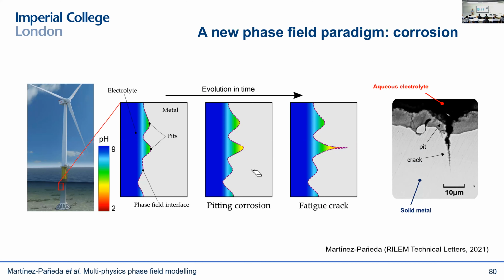It is a complicated problem. There's too many things happening in there, and all these things are important. It's very strongly coupled. So let me just showcase, for example, corrosion fatigue of offshore wind turbines. And this is, by the way, the problem that limits the service life of offshore wind turbines. So we're working with Vattenfall and other industrial partners in trying to figure out whether they need to start decommissioning those offshore wind turbines, or they can leave them there for a longer time. And basically, what you see is that first you have these pits nucleating at the interface between the seawater and the metal. Those pits start growing, driven by local chemistry and mechanics. And then eventually you get this pit-to-crack transition and the propagation of fatigue cracks.